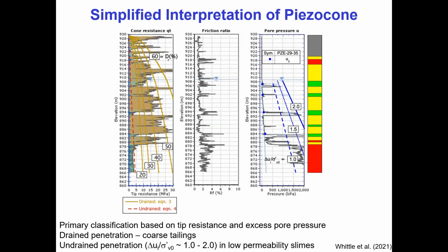This is the expert's interpretation of stratigraphy, and you can see the color schemes where it's brown, that's the tailings material, coarse or fine, and the green is the finer tailings. They don't distinguish slimes, but in my mind, this is slimes. We have very high excess pore pressures, similar to what we would find if we pushed a piezocone in clay. So we think this is the undrained response of the material. So our primary discrimination is to figure out drained from undrained behavior.